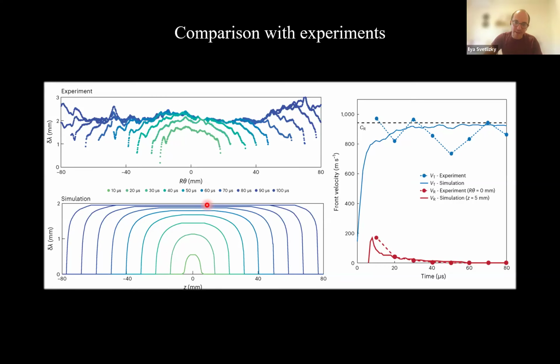Now, a naive argument would be that according to Jim Rice and co-workers, you can estimate the stress intensity factor very far away by integrating the curvature with some kernel. So meaning the more curved the crack is here, the higher the stress intensity factor it imposes very far away, something along these lines. So maybe that fails, or this should be corrected to some extent when your crack is still within the cohesive zone. This is what I'm thinking about. But I don't know how to make any better argument.